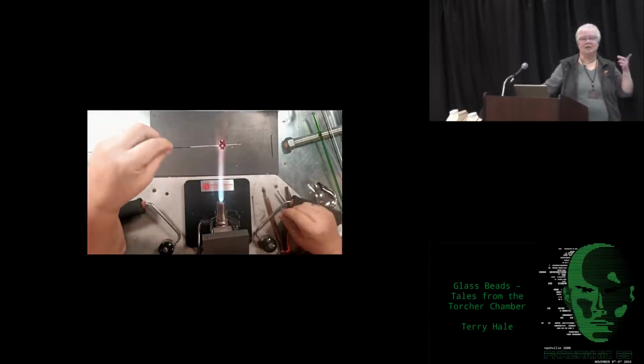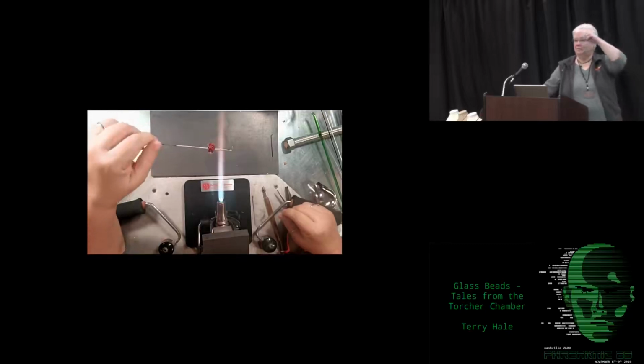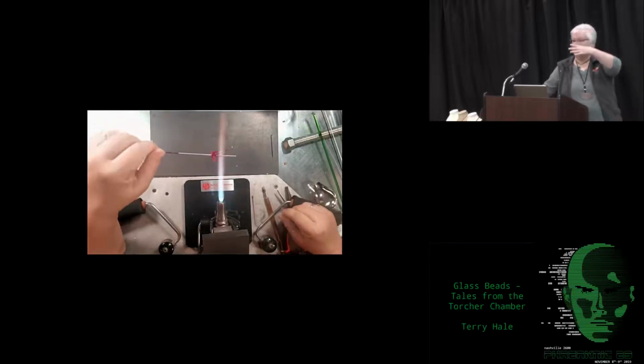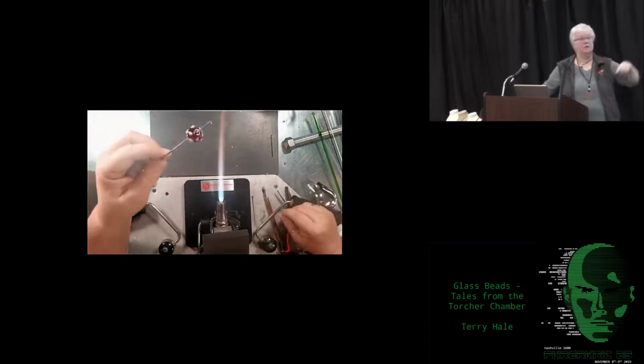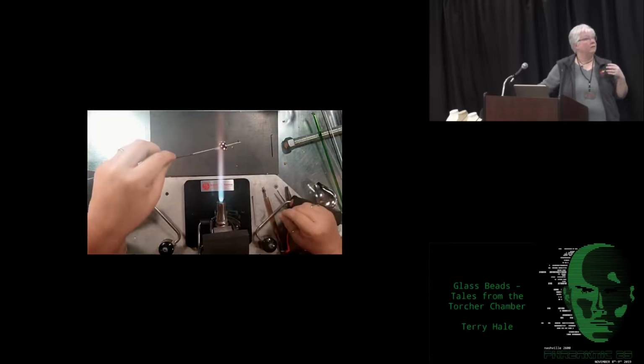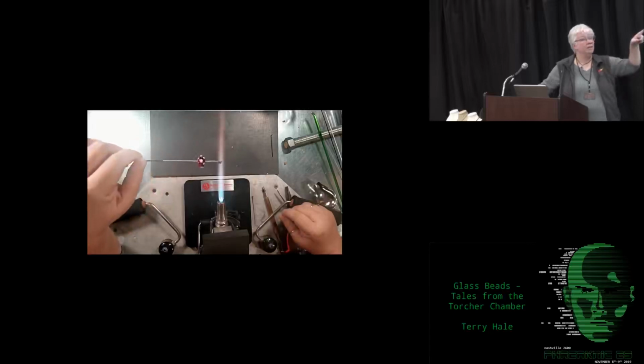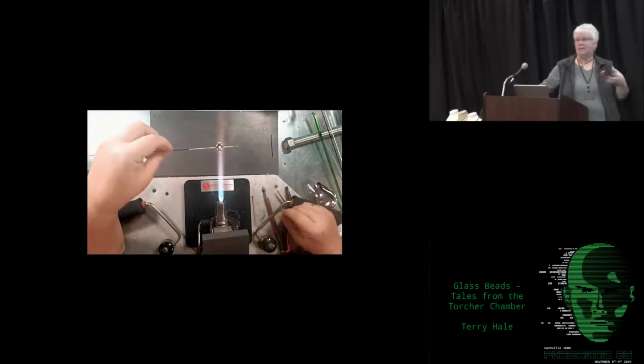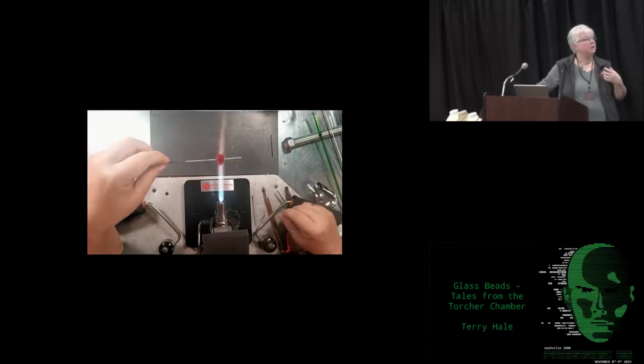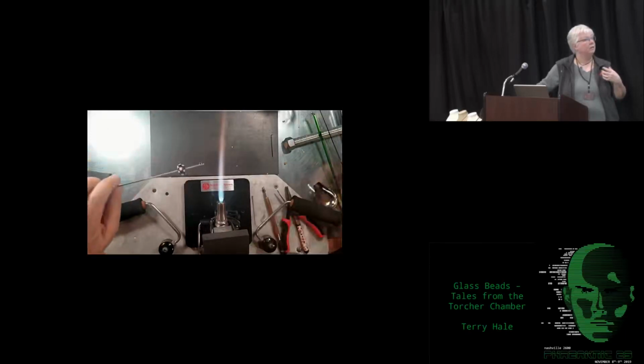Now, as you melt those dots, they sink in or smooth out. So I can leave the dots standing up, or I can melt them until they're actually smooth with the surface of the bead. And right there, I'm just trying to check and make sure everybody's melted in. You see the dots disappear. They turn clear, and then you come out of the flame and they turn back to white. So when I see that clear where the white should be, I know how hot it is. It's running extremely hot. There you go. All the dots are disappearing. It's trying to melt them in, and then they come back. And then once I'm happy with that, I'll grab some black.